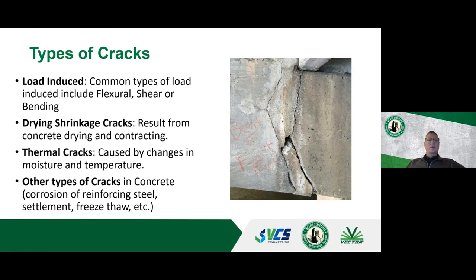The drying shrinkage cracks, the thermal cracks, those result from, again, ACI has a document that talks about the root cause of cracks, and I think it's 43 pages long, and it references about 5 other articles for more information, so you can really dig deep into this subject. But basically, a lot of this comes down to the initial shrinkage cracking: the concrete element you have, especially when you pour it new, has different forces going on within it.